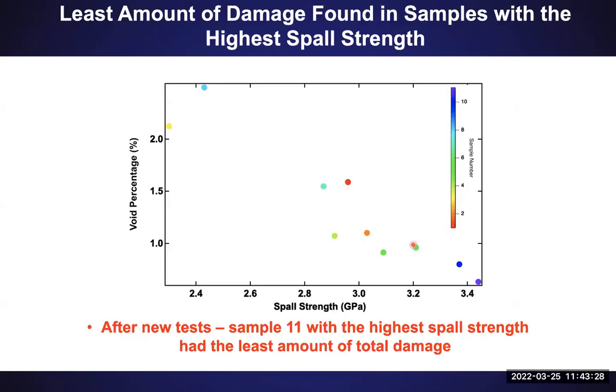We don't just like taking pretty pictures. We actually take those pictures and quantify the total amount of voids present in the material, only in the Spall plane. We normalize when we do our analysis, making sure to subtract any porosity that was in the material before the shock experiments were done. So here I plot void percentage as a function of Spall strength, and you can see that as the Spall strength goes up, you have lower amounts of voids present in the material, which should be the case.